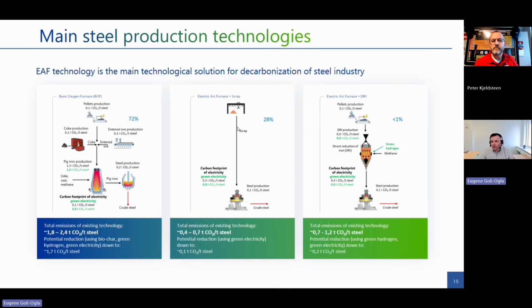And now more and more people are looking at the possibility of an electric arc furnace, and then it's actually only two operations: scrap plus furnace, and nothing in between. And for the furnace, you need electricity. And if you could get electricity from green sources, from wind for example, then you will have even less pollution. Then there is also the possibility of scrap plus DRI, which is directly reduced iron, and then to have some kind of balance in using scrap and in using this DRI, which also comes from pellets. And each process has advantages and disadvantages.